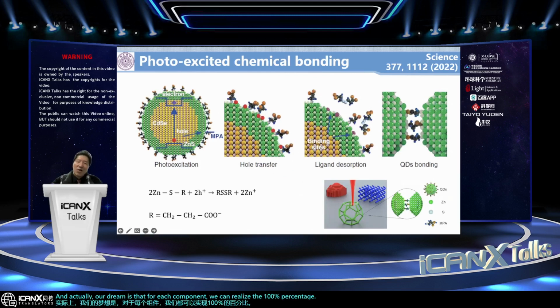Actually, we found the solution. In our strategy, we directly use the nanoparticles. We don't use any photopolymer. And we introduce some ligands at the surface. They are very small molecules. They consist of only 2 or 3 units of saturated chemical bonds. Then if we excite the semiconductor nanoparticle, the holes and electrons will be produced, and they can excite the surface ligand. And then if two nanoparticles are sufficiently near, the two nanoparticles will immediately adhere together.